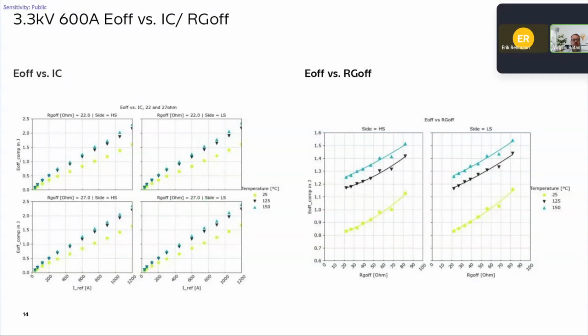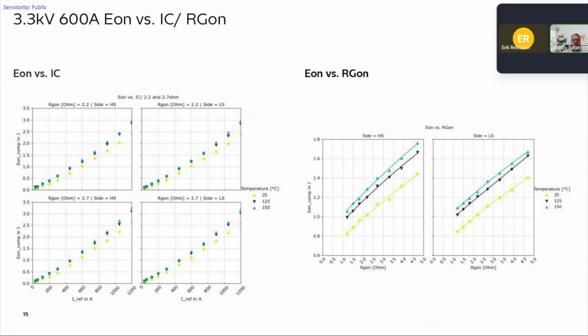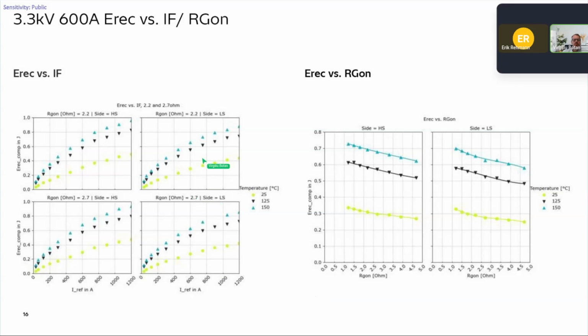Here are some examples of scaling of turn-off versus current, current series, the losses, and you can also see the RG influence. So even at higher RG, you can play with RG to make it a bit softer or faster or slower. Even in turn-off, and of course turn-on, very sensitive to changes in RG, current series over the temperature range. All of this is of course available also in the data sheet, and also for the rectifier, for the diode recovery. Current series is, of course, inverse against the IGBT.